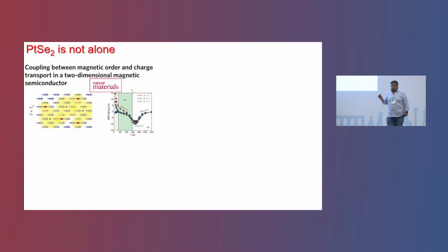And the good thing is that all the talks you have seen about two-dimensional materials in this conference were about intrinsic magnets, meaning that their bulk form, their mother form, is also a magnet. But this platinum diselenide and the other materials that I will be showing are non-magnetic in the pristine, bulk form, and you need to thin it down and then create some defects. And platinum diselenide is not alone; there are lots of materials which show this kind of defect-induced magnetism in the monolayer limit.